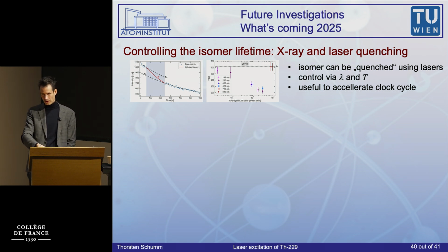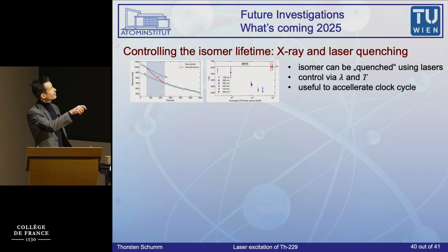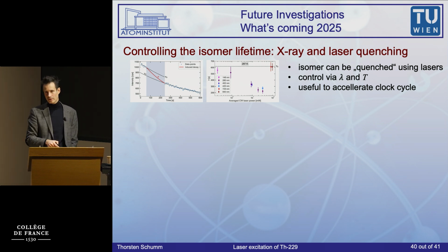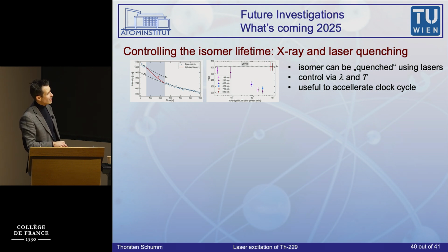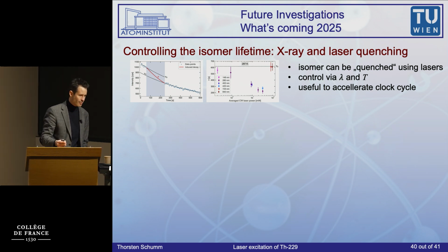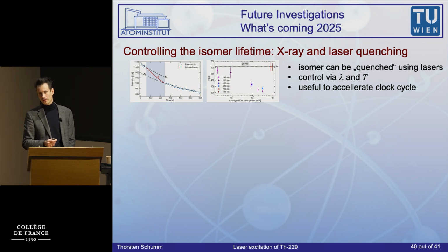We call this quenching. Okay, so we can laser excite the nucleus, and then the spontaneous decay starts. But then we shine in a laser here. We've also done it with X-rays, but laser is simpler. And then that actually accelerates the decay, and when we turn off the laser, it falls back to the 11 minutes lifetime. Okay? We first thought we have to excite electrons above the band gap for this to happen. Turns out the blue laser pointer does the trick. And we don't know why yet.